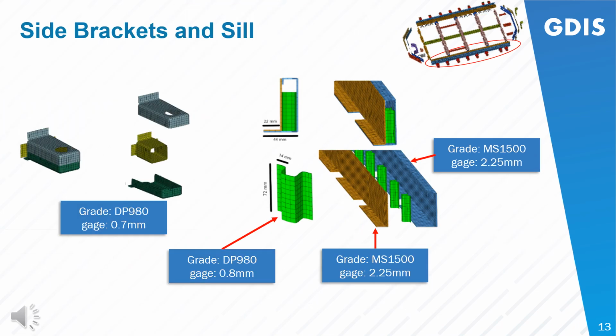The side structure consists of the major component, which is the side sill. Inner and outer are both made out of martensitic 1500, 2.25 millimeter thick, with internal bulkheads that are strategically distributed throughout, and these are made out of 0.8 millimeter DP 980 material.